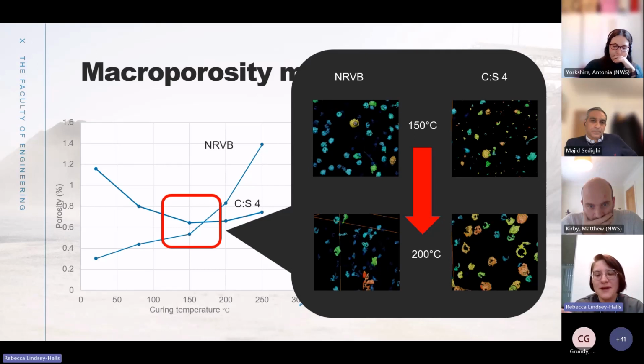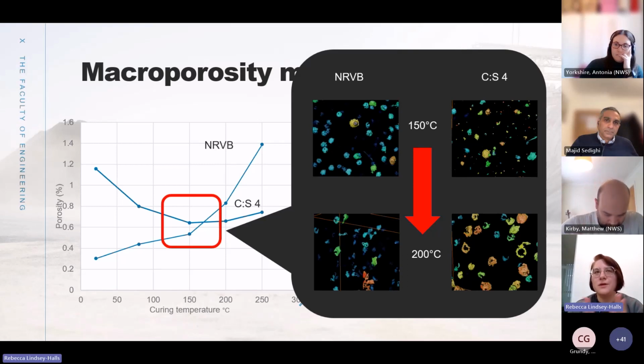So what's growing inside these pores? I know the mineralogy and I know the pores are changing shape, but I don't know what is growing within these. So we actually have plans in the new year to go down to the Diamond beamline and use their DIAD facility. This has the capacity to XCT scan them, so you're getting these images, but then you can also click and it gives you an XRD pattern, so you also see what's where.